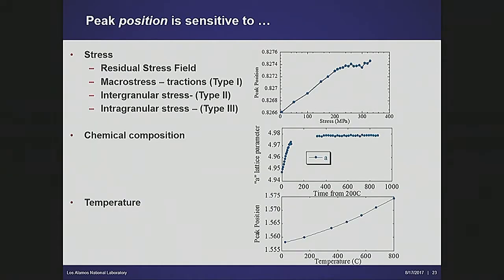From the peak position, if you put a load on it and measure changes in this position, you can relate it in principle to the macrostress, type 1, type 2, possibly even the type 3 strains in the material. It's worth noting, though, that the peak position is also sensitive to chemical composition, the D0 problem, that you've been exposed to, and temperature.